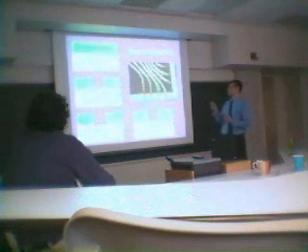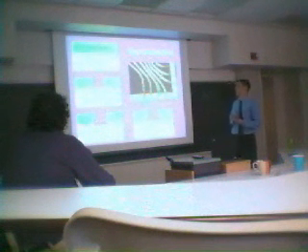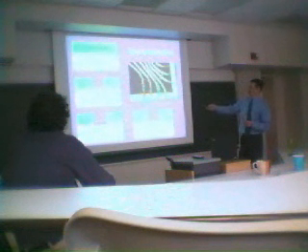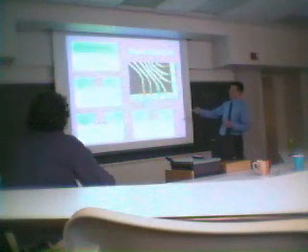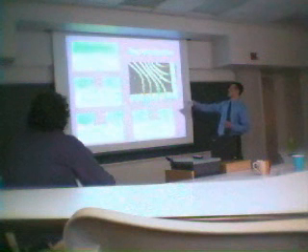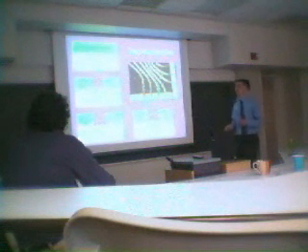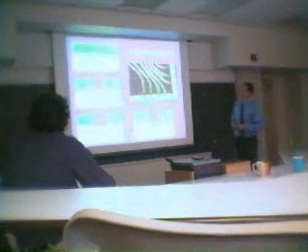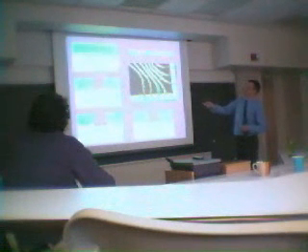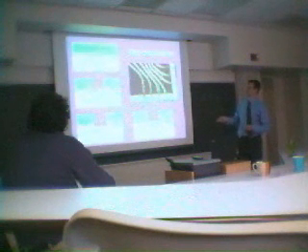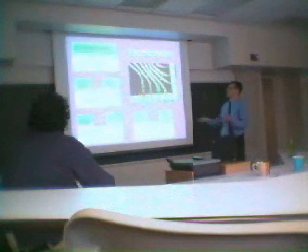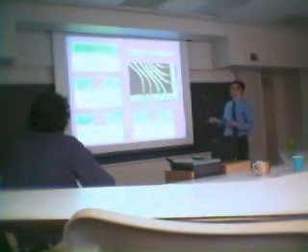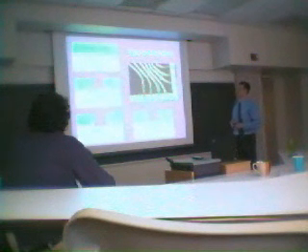Now, this is really not a conventional application for photolithography because photolithography typically deals with flat surfaces, but this has these really long, deep grooves in it. And so to get around that, what we did was we used the dry film photoresist. Initially I tried doing this by applying the dry film photoresist to the alumina first, and then doing all the standard procedures. But the problem with that was that it left a residue that could not be cleaned